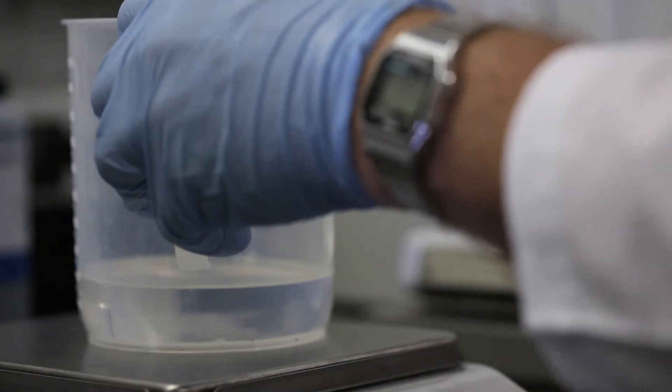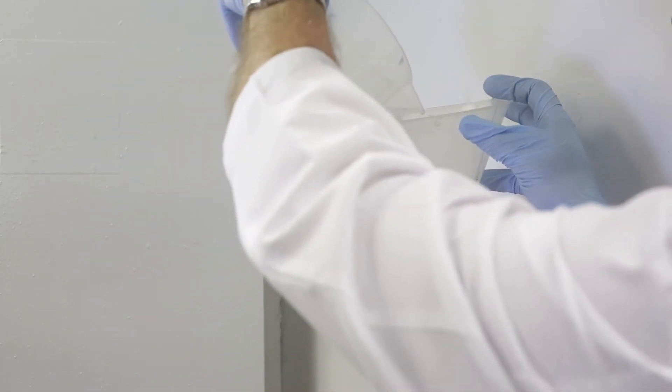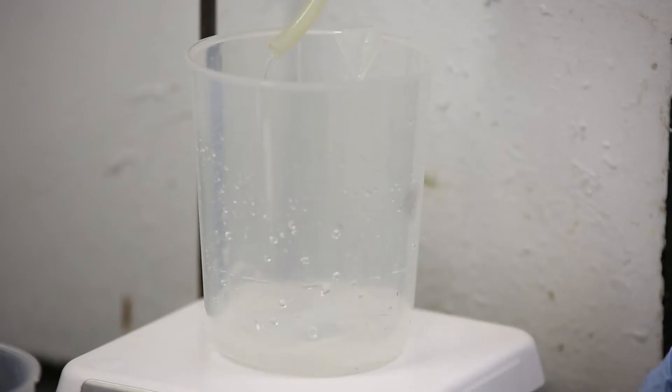Next, we place water, surfactants, and seed in a glass laboratory reactor, equipped with an agitator and condenser, and heat them to the polymerization temperature – usually 60 to 80 degrees Celsius.